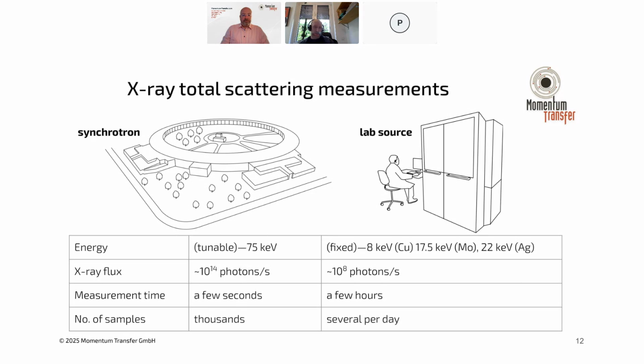And the measurement times to get a very good pattern for quantitative analysis with a device like that is typically a few hours. And I can say in my previous research position, we were often measuring samples overnight for 8 to 10 hours when we wanted to get a really good pattern to publish in a paper, for instance. You can do very quick measurements in some cases, but the ability to really quantify things or to detect trace levels of components is very difficult in those cases. And typically you can measure a few samples per day if you want to collect that kind of quality.